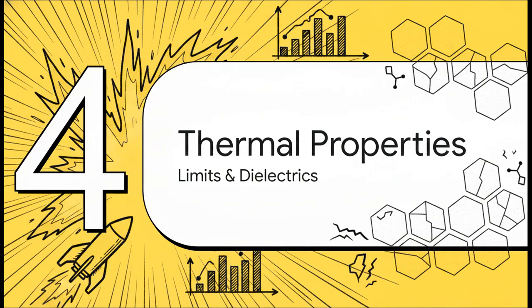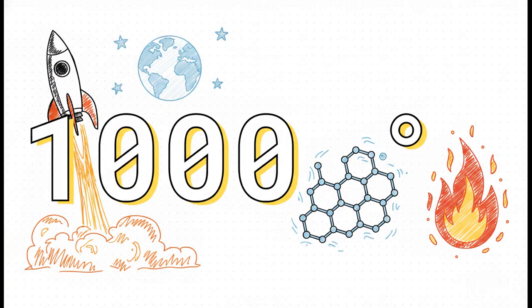All right, Section 4, Thermomechanical and Dielectric Properties. Let's look at the actual hard numbers. What can this consolidated material survive in the field? 1,000 degrees Celsius. That's the impressive threshold before hexagonal boron nitride even thinks about oxidizing in ambient air. Up to that point, it just forms a nice protective boric oxide layer. And if your systems are operating in an inert atmosphere or out in the vacuum of space, it stays structurally stable up to a staggering 2,000 degrees Celsius.